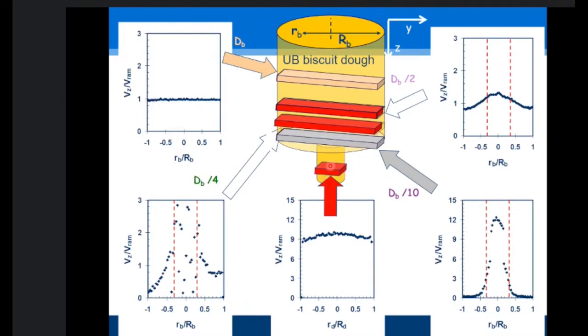If we go down to the one at the bottom here, this is in the die land, as we call the section that you're extruding it through. There's your velocity over the RAM velocity. It's much bigger than one because it's a narrower area. You can see that this is all normalized against the die land radius. It's almost the same velocity. And then as we get towards this, you can see that it starts to accelerate as it gets towards the middle. And that's what you expect with a converging flow.